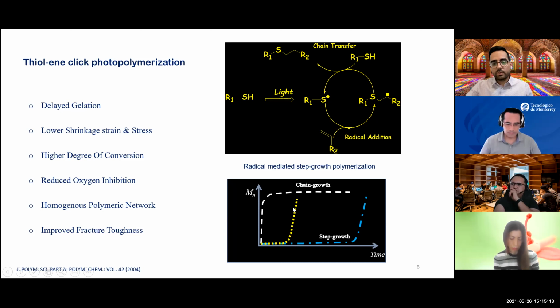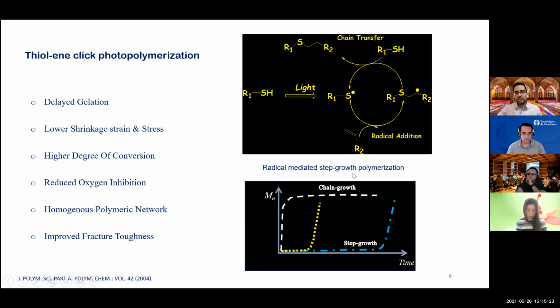Accordingly, the progress of the molecular weight for this system is in the middle between chain growth and step growth. So it's known as a radical-mediated chain growth, and it's step growth polymerization. So it's a mix combination of those techniques, and we can see different advantages for those systems. We can see delayed gelation, we have lower shrinkage strain and stress, we can see a higher degree of conversion compared to the conventional methods, and we don't have any problems with the presence of oxygen because we don't have any oxygen inhibition in these systems.